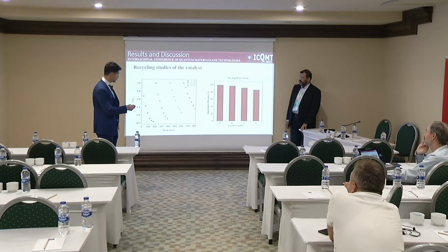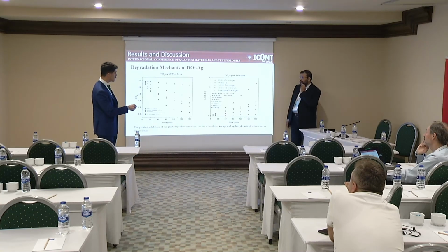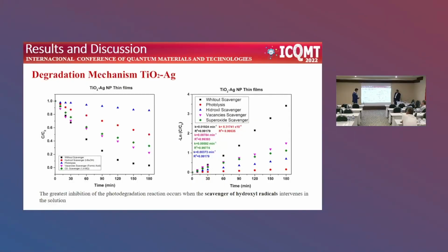This is the reason that I put this type. For example, for hydroxyl scavenger, I put formic acid. No, sorry, tert-butanol alcohol, because this species can scavenge this type of radicals. It's not an increase of the pH because it's not the same species. You are confusing this type of species. It's not the anion of the proton. It's a radical species.